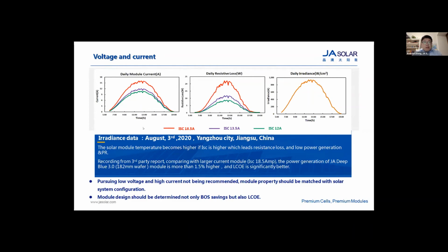Obviously, we can see from this graphic that the solar module temperature becomes higher if the module has larger current, and this leads to significantly more power generation loss. And the recording is actually from a third party as well. Compared with the large current module, the power generation of the DeepBlue 3.0 module is more than 1.5% higher. And of course, the LCOE is significantly better.